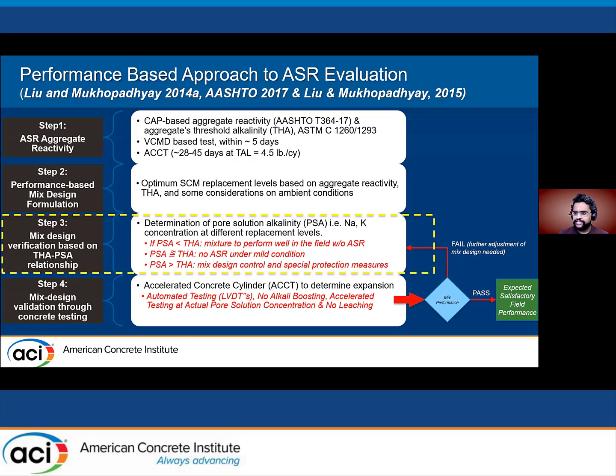And at this stage, it's just a comparison assessment. Is the pore solution alkalinity of my mix lower or higher than the threshold level alkalinity of the aggregate that would be used in the structure? If it's lower, then it's not a problem. If it's equal, it would perform well, but only under mild conditions. If it's greater, then the mix design probably needs revision with a higher SCM dosage.